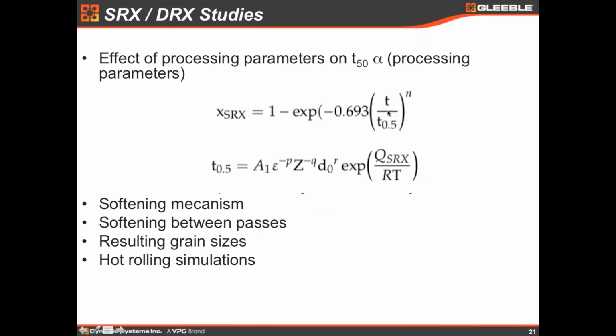So it's easy to derive, by performing mechanical testing, the time for 50% recrystallization or 50% softening. We consider for austenite that they will be equivalent. And this time for 50% softening will be proportional to the strain, the Zener-Hollomon parameter, or the strain rate corrected by temperature, and the initial grain size. This is the activation energy for static recrystallization, the gas constant, and again, the temperature. So we have a way to derive the T50 and correlate that with the actual processing parameters or experimental parameters. So that's why it became very popular to use the sigmoidal curve equation in this form.